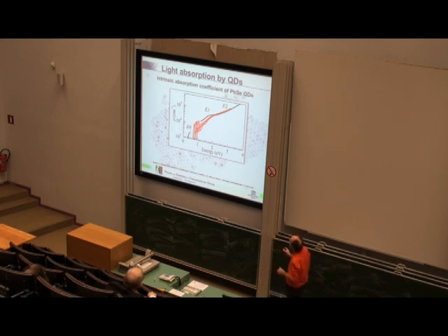Typically it looks like this. What we plot here is what we call the intrinsic absorption coefficient. What's the meaning of that? Think of a thin film of quantum dots. If you invert this number, it's more or less the film thickness that you need to absorb all the light. So a number 10 to the 4 here means in a film of 1 micron, I will absorb all the light with this wavelength, for instance. We get here this absorption coefficient as a function of wavelength or energy. I use the photon energy here.